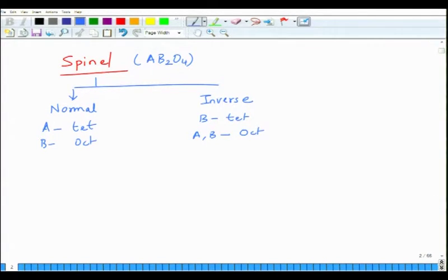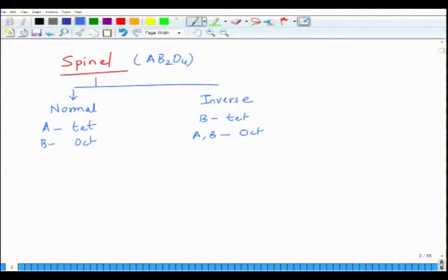We can see that the unit cell in this case is typically made of 8 formula units, to accommodate these interstitial atoms in a regular periodic arrangement so that you can form a lattice. The lattice does not come in one formula unit. You have to put in 8 formula units of AB2O4 to put these atoms in the interstitial positions in a repeatable manner. So, the lattice is a little bigger.